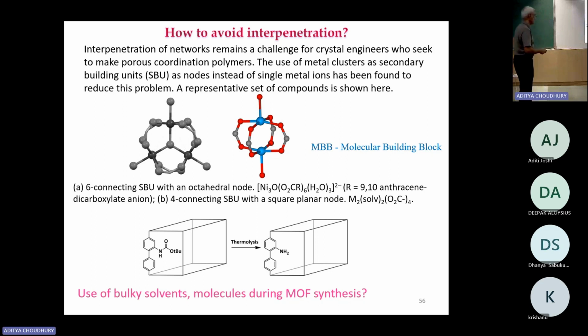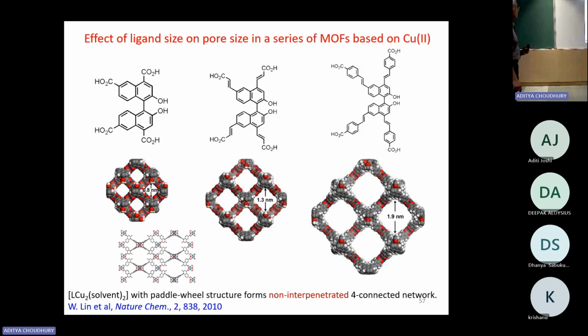The other way, and we are going to see it later: you make a MOF with a large side chain that will occupy the empty space. You also have a ligand here, everywhere, because this bulky substitution will occupy everything, which prevents any interpenetration. What he does is he removes this by heating it. The whole tertiary butyl group can be removed. By removing this, he creates a lot of voids. So that's a tricky way. This is what is called PSM, post-synthetic modification. So this is the way you can avoid interpenetration.